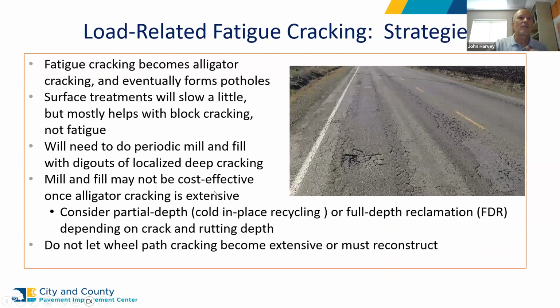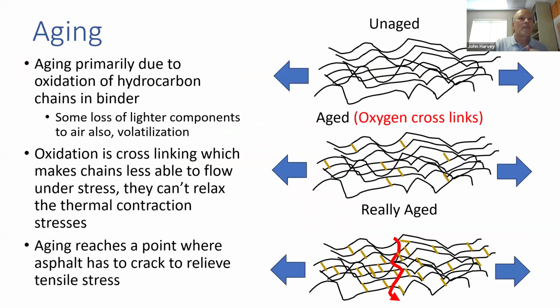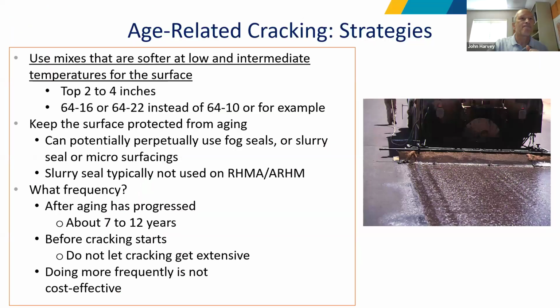Yes, well, the PG specification has 2 parts. The first part is the high temperature. Keep the same high temperature of your binder. That's the rutting part. That's rutting resistance at 64 C, which is like 150 Fahrenheit. But what I'm talking about is you can ask for an asphalt that keeps the high temperature, but goes to a lower temperature on the second part of the spec. So go to that lower part of the temperature on the second spec, and you shouldn't be giving up any rutting resistance. So that's the answer to that question.